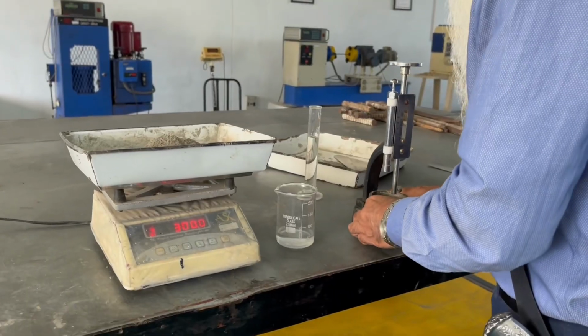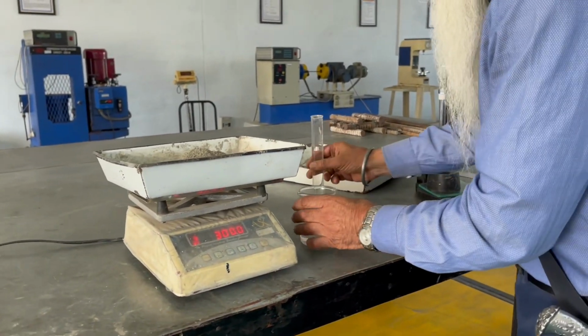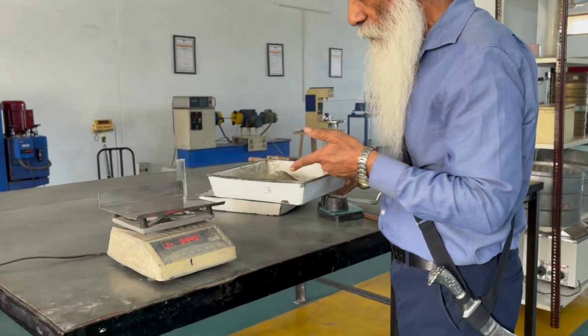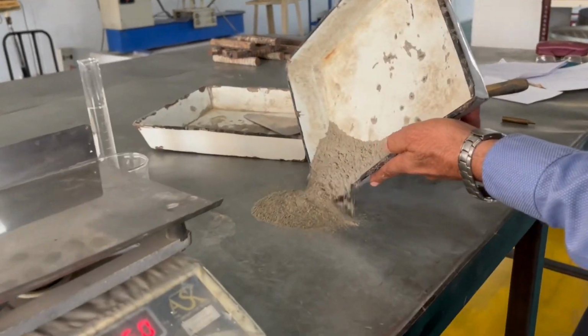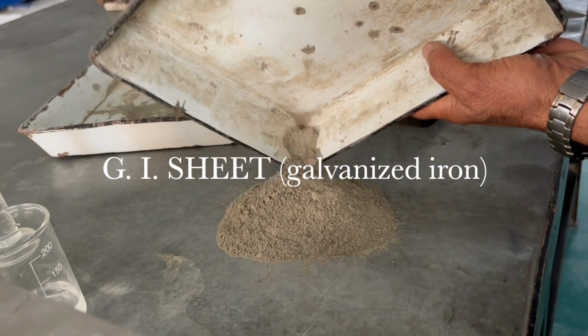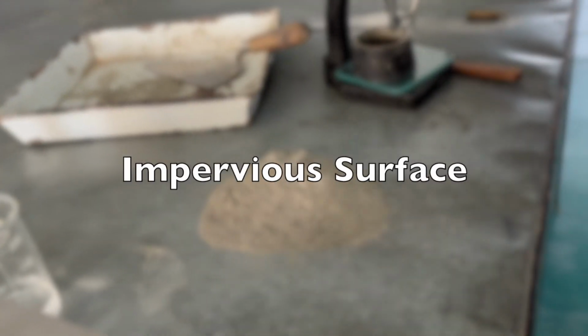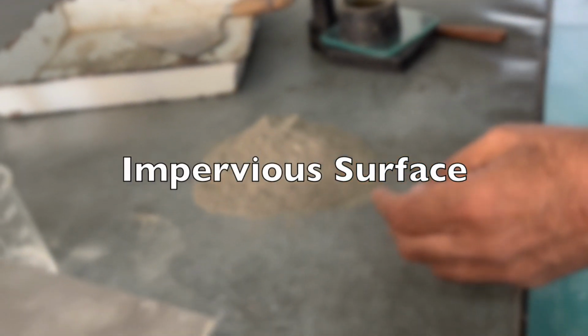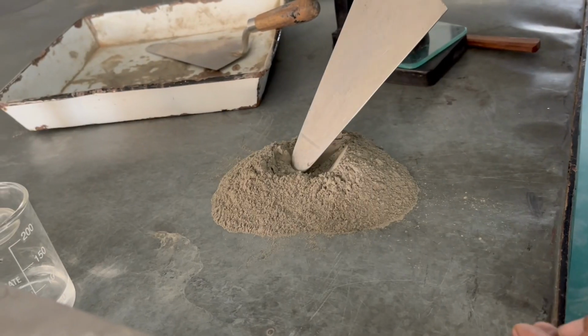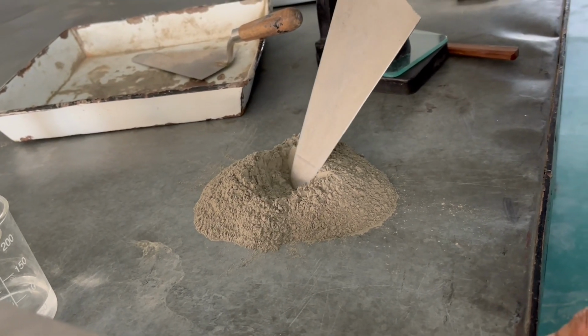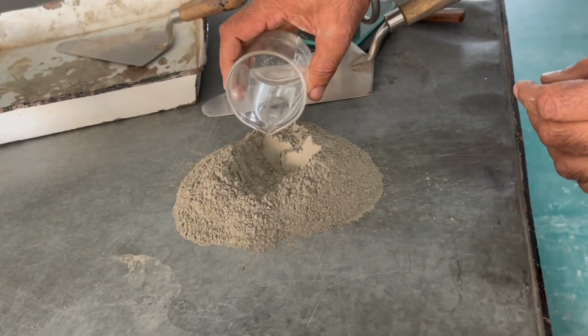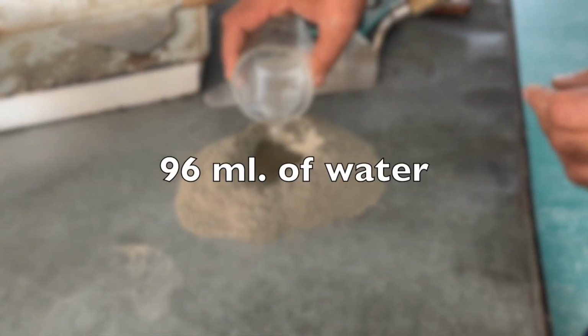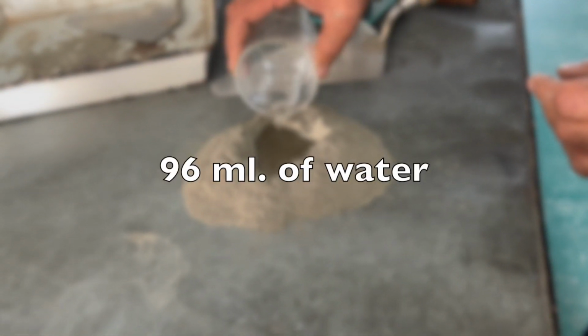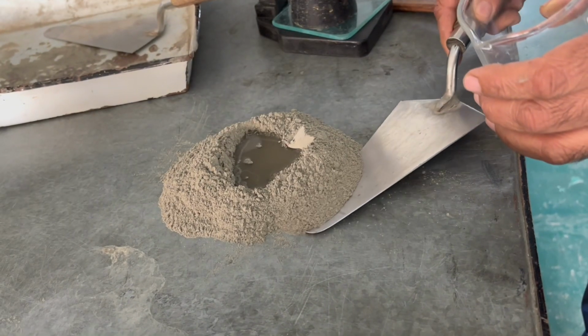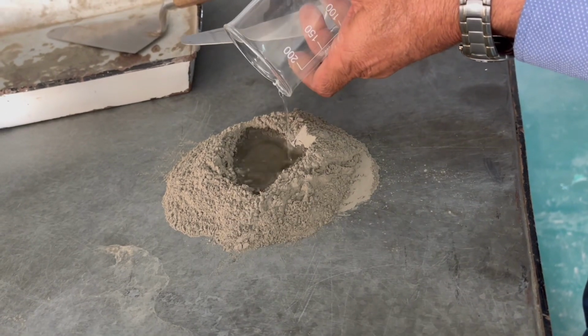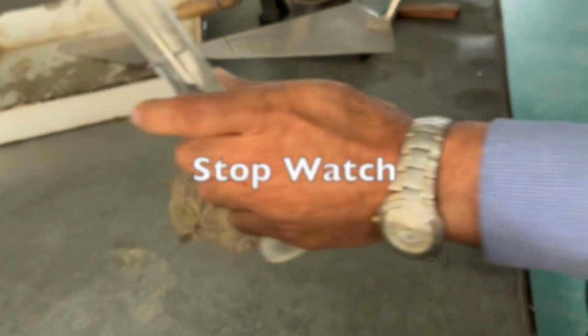It should be mixed on a surface that is impervious. So you can mix it in the tray. This table is of GI sheet, so it is an impervious surface. Here I can mix this by putting the water slowly and carefully. I will put 96 ml of water. This process should be done gently. And for this I have started my stopwatch.